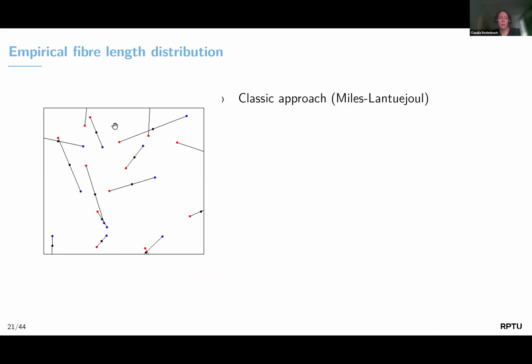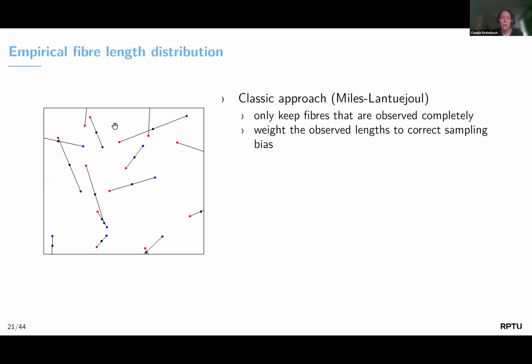A classical approach for removing such edge effects is an approach by weighting, which is called the Miles-Lantuéjoul, or also Horvitz-Thompson correction. The idea is you only keep fibers that are observed completely. This way, you introduce a bias because longer fibers are more likely to be cut by the edge of the window, meaning in the remaining ones, you have a bias towards short fibers. And weighting this with 1 over the probability of being observed can correct this particular bias. However, you see here in such an example, quite a lot of fibers can be cut and all the information for them is lost to the analysis.